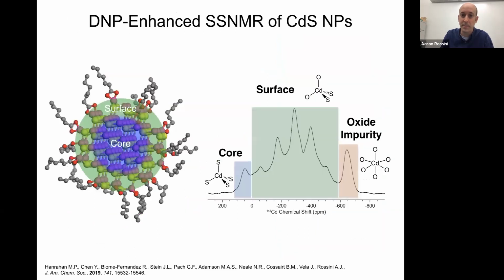So if we look at the DNP enhanced cadmium-113 NMR spectrum, there are 3 different signals we see. This signal at 50 ppm is from the bulk-like cadmium atoms that are coordinated by 4 sulfurs. Those are going to be found in the core of the nanoparticle. We have these surface cadmium atoms. They come in with enhanced intensity because this is a cross-polarization spectrum. Those are the cadmium atoms that are coordinated by carboxylate ligands. You're going to have some CH2 groups on those ligands that can provide the proton polarization to the cadmium spins. And then we have this third signal, which we know is an oxide impurity or byproduct of the nanoparticle synthesis.